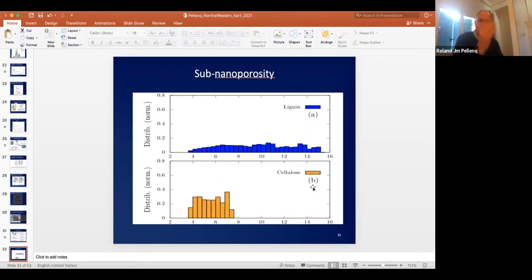All right, so that's going back to lignin and cellulose. You can see, as I said, that the cellulose is very compact because the pores are between 4 and 8 angstrom, not even 1 nanometer, while in the case of lignin, those nanopores extend maybe to 2 nanometers. By the way, this is what I will show at the end of my talk. This is not the end of the story. We are very much in the nanoscale of the porosity. Obviously, there is a larger scale porosity with larger pores anyway, right? But we were investigating those.